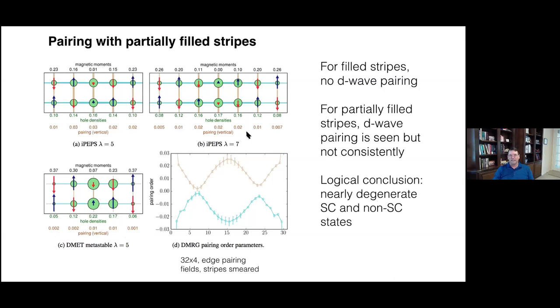Just to give you the digested version, what we find for pairing is that for filled stripes, there's no D-wave pairing, just gone. For partially filled stripes, the D-wave pairing is seen, but not so consistently. And so the logical conclusion from that is that there are nearly degenerate superconducting and non-superconducting states when you are in this partly filled stripe regime.